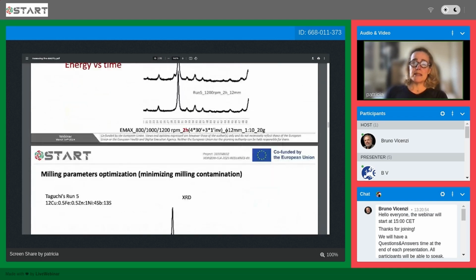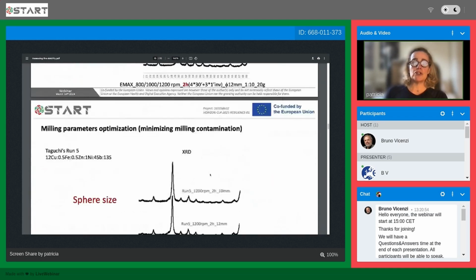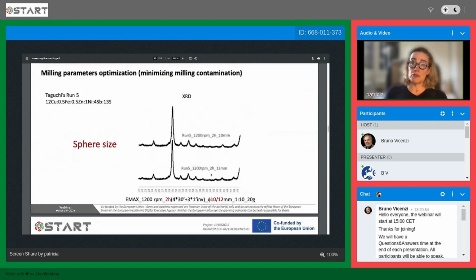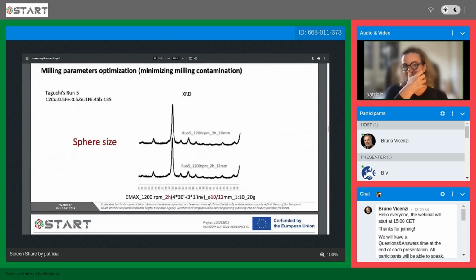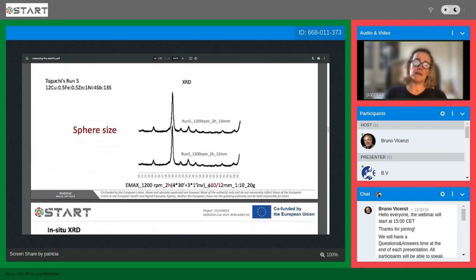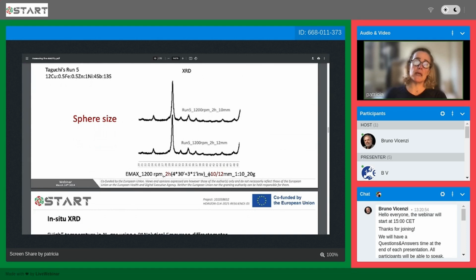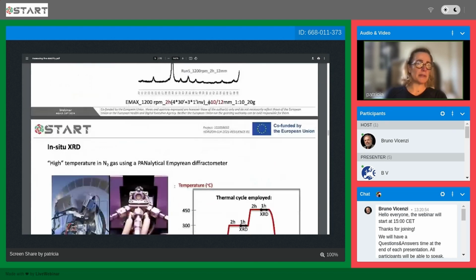The other thing we wanted to make sure was what kind of sphere should we use. And then it turns out that either 10 millimeters or 12 millimeters are suitable to achieve what we wanted. So in the end, this was what we have chosen as parameters.